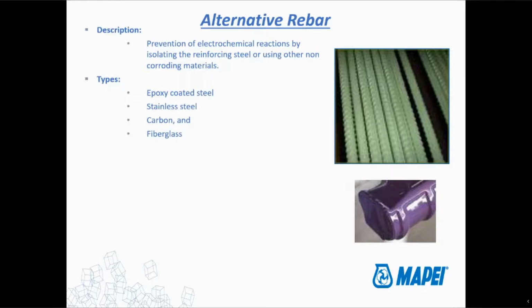Epoxy coated bars, it's kind of a contentious one. Some people are firm believers in epoxy coated bars. I happen to be in the camp that's not a big believer in them. I just feel by the time they get out to the job site, there's going to be plenty of pinholes from transportation damage and being lifted off the truck and dropped on the ground and everything else. It's really impossible to say that the bar is completely coated. And if you have even one small hole, as we talked about before, those chlorides are going to all migrate to that one small hole and really attack the steel all at that one location, which is going to be really bad in the long run.